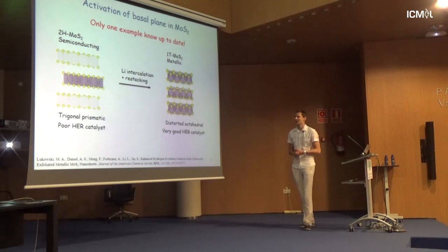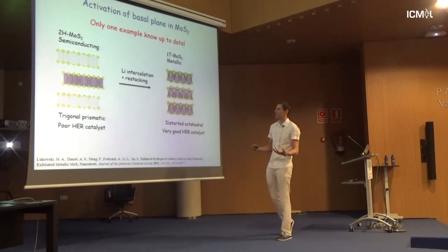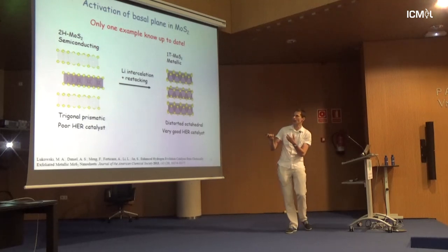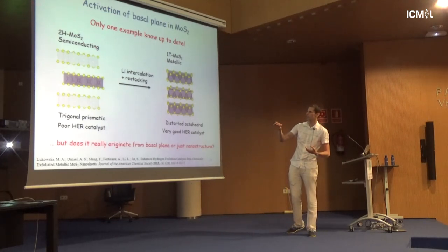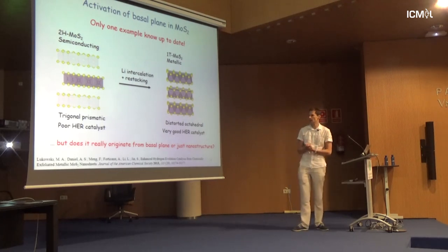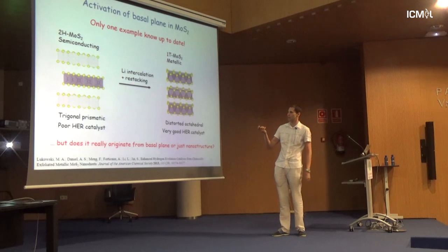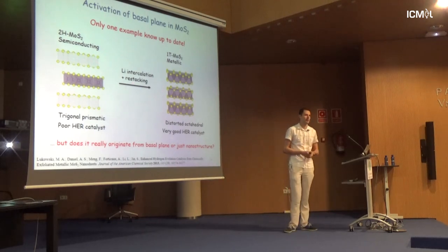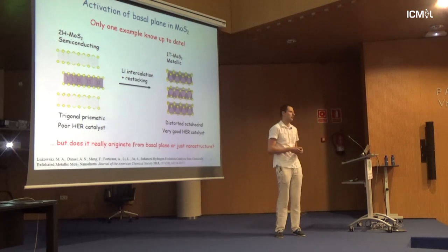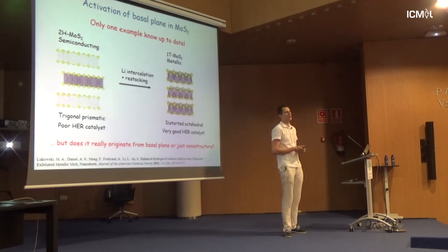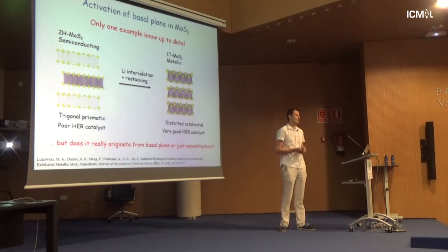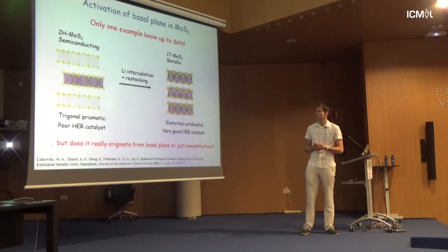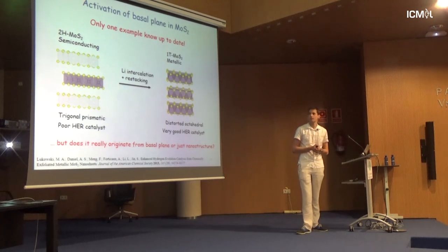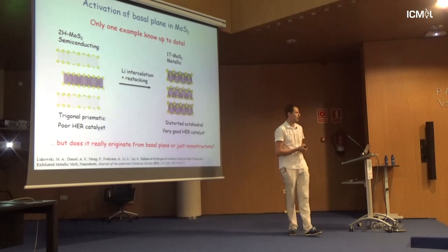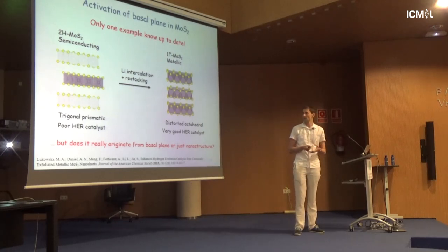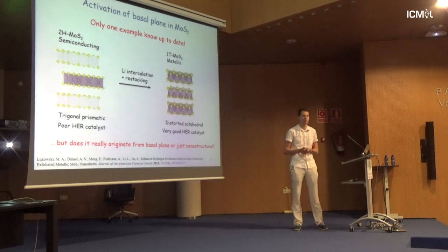There's one, and because it's molybdenum sulfide, you can turn the semiconducting molybdenum sulfide into metallic molybdenum sulfide. But you do it in a little bit complex way, so you need to intercalate lithium with the notoriously, famously known butyl lithium, which caused a lot of damage to science in the US. So there was this classical accident with butyl. So not exactly something you really want to work with in your lab without a glove box. Well, we have a glove box, so we work with butyl in the glove box.